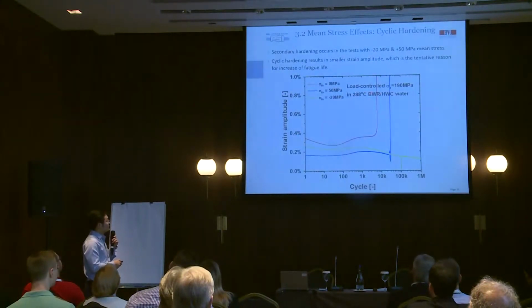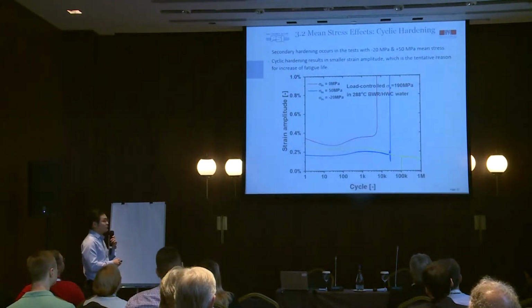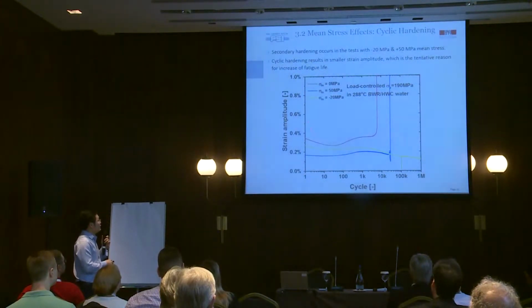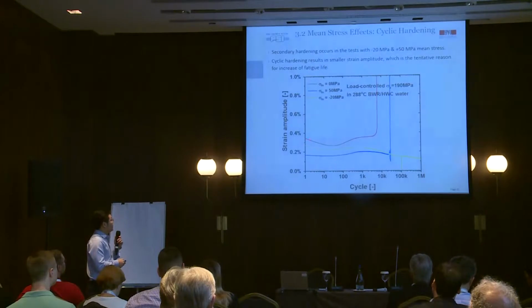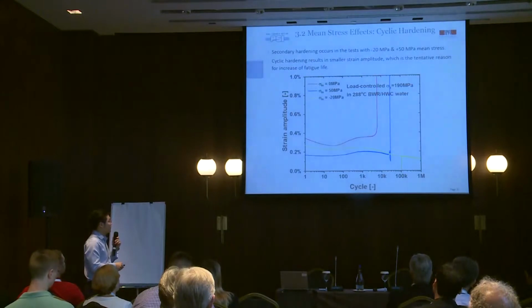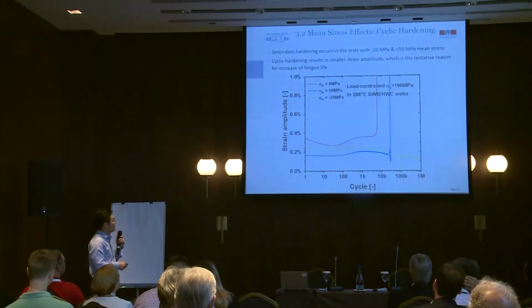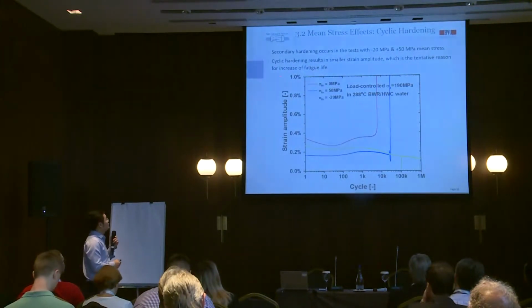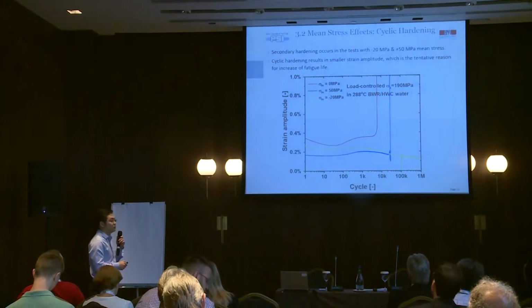If we take the test result example with a stress amplitude of 190 MPa in high temperature water, this is the strain amplitude corresponding to the loading cycle. We found that the test with mean stress has undergone two phases of hardening: the first hardening and the second hardening. Especially the test with minus 20 MPa has the most pronounced second hardening. The second hardening results in smaller strain amplitude, which is a tentative reason for the increase of fatigue